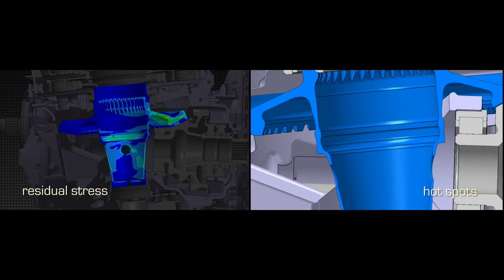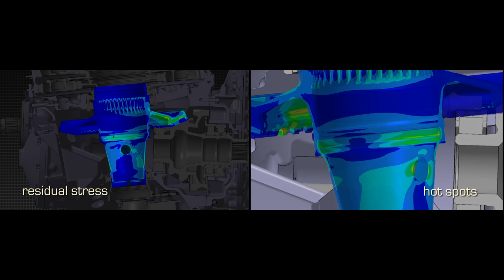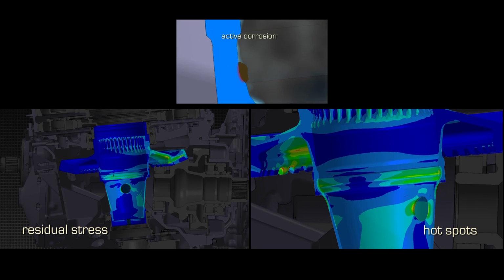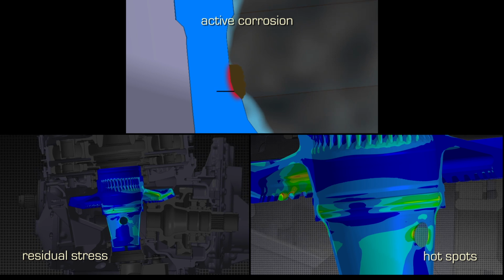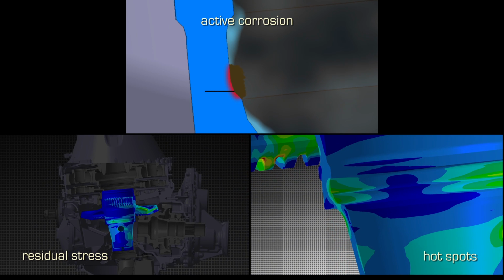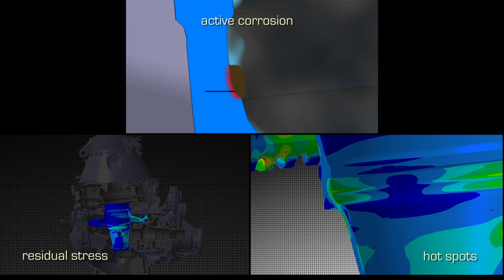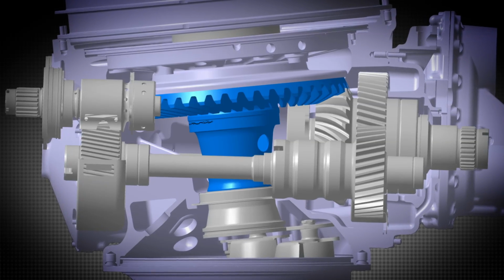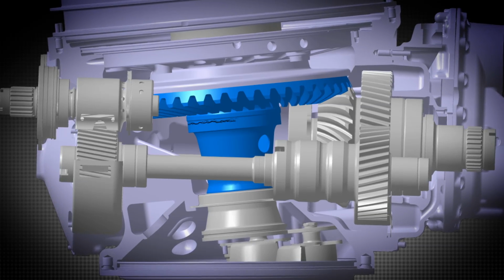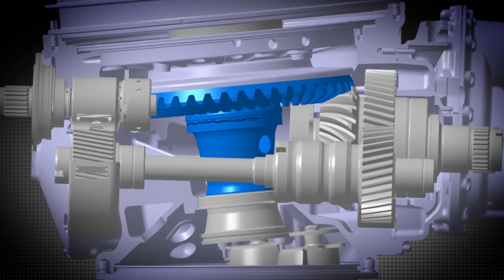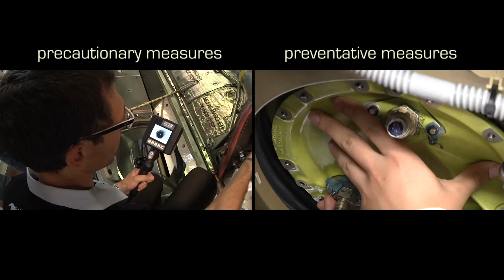The residual stress and hotspots factors, even in the presence of active corrosion, are not sufficient to initiate a crack. To initiate a crack, all three factors, above all the active corrosion phenomenon, must be present. Once a crack has initiated, it gradually grows or propagates around the circumference of the bevel gear vertical shaft.